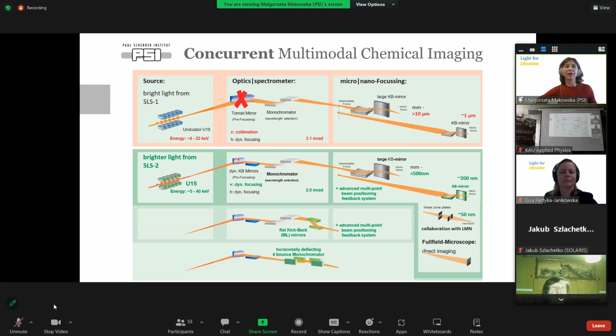So instead of one pre-focusing mirror, which was focusing horizontally and vertically collimating, we will have dynamic focusing in both directions. So as I said, we will also have a different undulator, and we are aiming for an energy range up to 40 keV, so significantly higher than up to now, but we stay with this 5, so we still have some overlap with tender beamlines.